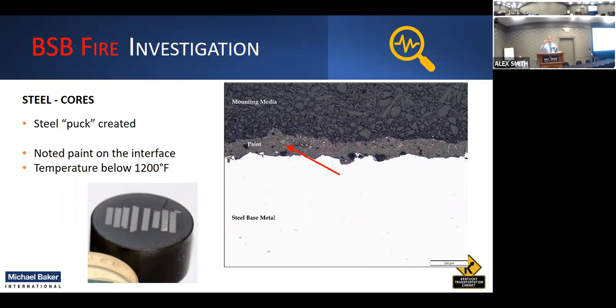And since there was still a little sliver of paint, I couldn't see the paint from the puck we took, but there was a little bit still left on there, at least to the metallurgists, those people doing it, giving an indication of the temperature that the fire got to.